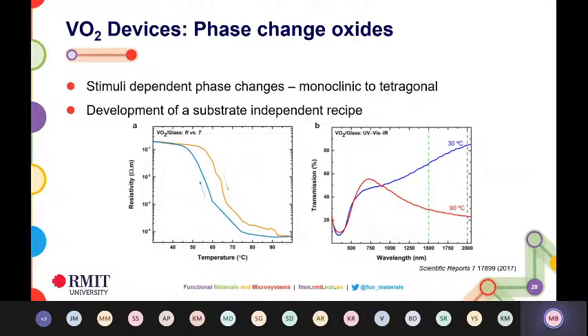material. It's a material which actually changes phase from being an insulator at room temperature to becoming a conductor once you heat it up to around 70 degrees centigrade, and then switches back to being an insulator once you cool it down. The fascinating thing with this material is it not just changes its electrical properties, it also changes its optical characteristics with heat. So you can see over here, the optical characteristics in the IR region of the spectrum is quite different when you heat up the sample from 30 to 90 degrees centigrade.